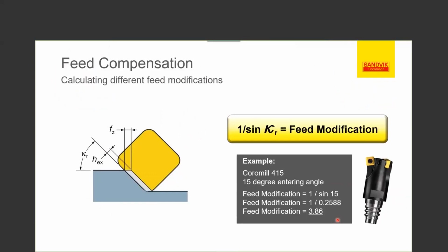So how do we calculate that? It's very simple. We basically take the sine of the angle of the insert, take its reciprocal, and that will be our feed modification factor. So if you have a high feed cutter with a 15-degree entry angle, for instance, we take the sine of 15, which is 0.2588. We take its reciprocal. Your feed modification factor will be 3.86. So basically, if you have your feed per tooth of whatever it is, you multiply it by 3.86, and that will be your chip thickness.